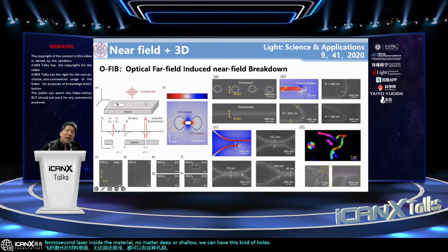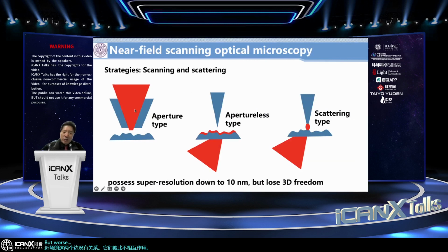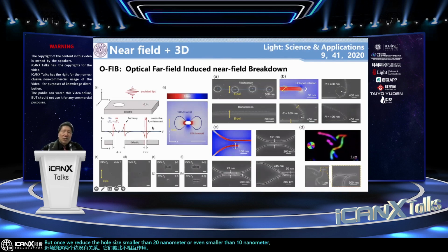If we shine light on the hole, we will have this kind of near field, as I told you. This near field decays rapidly, generally within 10 nanometers. If the hole size is very large, these two side near fields have no relation. They don't interact with each other. But once we reduce the hole size smaller than 20 nanometers, or even smaller than 10 nanometers, these two near fields will interfere with each other. And the interference result is that the local light field strength becomes much stronger, even one order stronger than the initial incident light field.